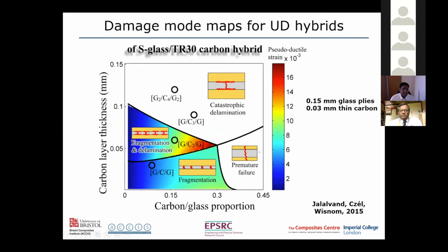So if we have too much carbon, we get this premature failure, the whole thing fails catastrophically. If we have less carbon, but it's thick, then we can get this catastrophic delamination. Neither of these are what we want. But if we have sufficiently thin absolute ply thickness and not too much of the carbon, then we can get this fragmentation and delamination, or just fragmentation on its own. And this gives us the pseudo-ductile gradual response which we want.